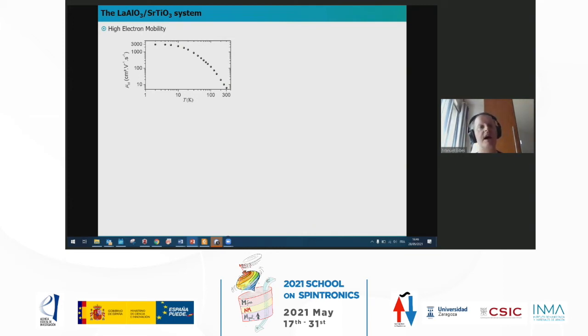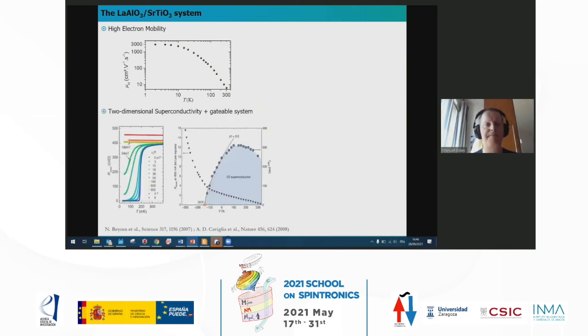It has a quite high mobility at low temperature. Here you see we have 3,000, but in some samples, some authors have reported, I think the maximum is around 140,000 by a group in Denmark. It is superconducting. This was discovered for the first time by Jochen Mannhart and Jean-Marc Triscone. And it is also gateable because it's a 2D system.